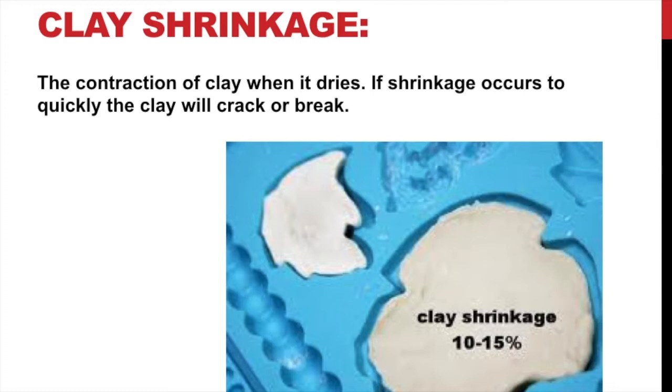This is really important when making pottery. If it's getting leather hard and something breaks off, and you try to take plastic clay and attach it to leather hard — especially bone dry clay — it's not going to work. It'll eventually come off because the clay is going to shrink at different rates and it's not going to stay together. So make sure pieces are in the plastic or the more moist leather hard stage when you're making things.